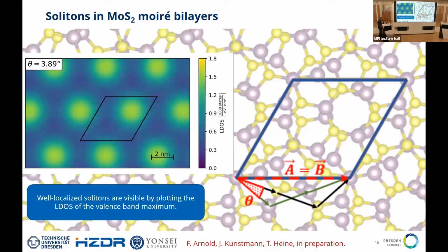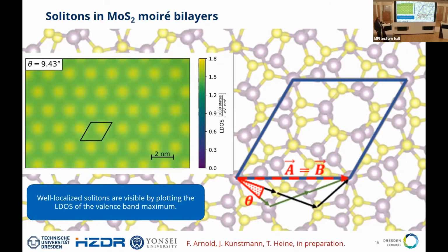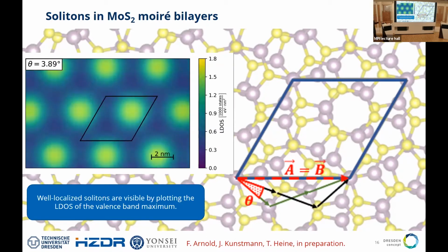And you can see what the soliton is doing. So, I mean, this is essentially what you would actually expect, right? You change it, and you change, of course, the size of your unit cell, and there it changes. All great. There's one problem. That is one thing that you see very often in calculations. People took planar MoS2, put it on top of each other, and they were rotating it. But of course, reality is a little bit more complicated. You have a relaxation in the structure in the Z direction. And that relaxation is very difficult to monitor experimentally, right? Because you simply don't have a means to see that very easily.